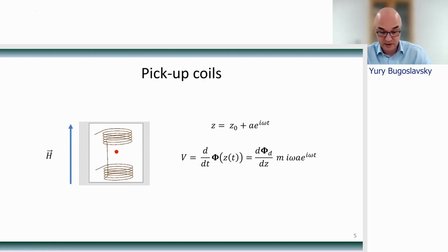One important consequence is that the sensitivity of the coil increases if the coil is smaller. So to make a very sensitive device, you would want to have the coil size as close to the sample size as practically possible.